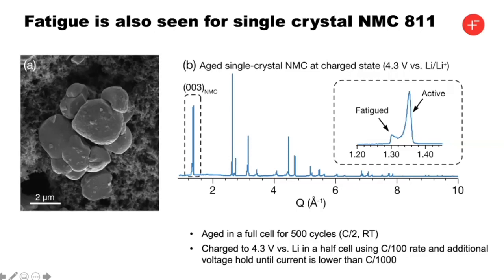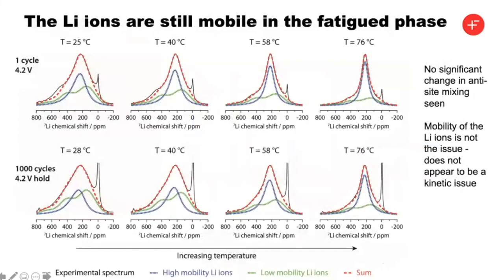And so we started to investigate this via single crystal 811. And you can see a material now that's also been cycled again. This is aged in a full cell for 500 cycles, pulled apart against lithium metal. And again, you have the same phenomena of fatigued phase where the C parameter doesn't collapse and an active phase that is behaving normally. So it doesn't seem to be associated with the particular primary secondary configuration that you get in the traditional 811s.